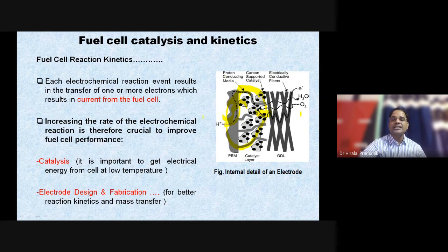So the ion is coming from the anode side to the cathode side through the electrolyte, and the electrolyte present in the structure of the electrode will help the ion reach the catalyst sites, right? And oxygen will also reach the catalyst sites from the outside. The H+ ion and the electron, which is coming from the outside circuit, must also have a path for electronic conductivity, and then reach the catalyst sites.